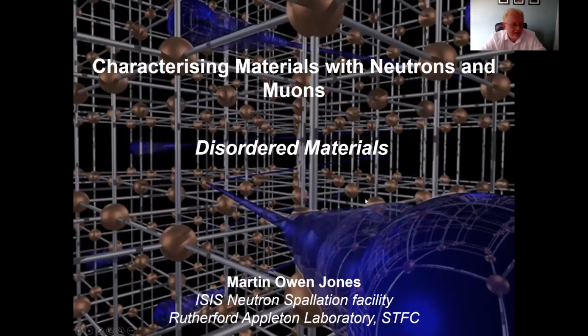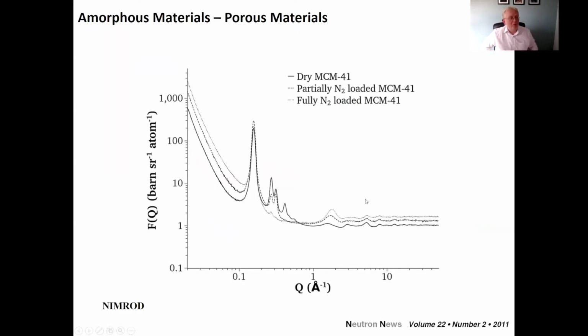We can also look at disordered material. Normally people might think of disordered materials as glasses. Here we have something called MCM41, which is a mesoporous material. And we've got 3 sets of data here. We have this solid black line, which is the lowest line, which is the dry material. And then we have this dotted line, which is the middle line, which is partially loaded with nitrogen.